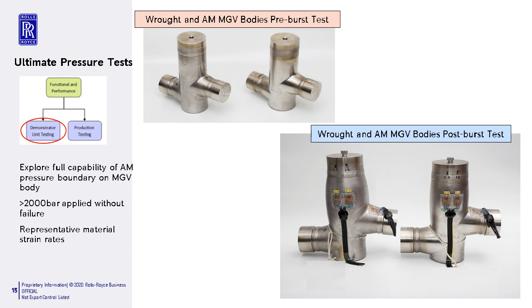And this rig was able to go up to around 2,000 bar. So we're really trying to blow up the valves. What we found was that both valve bodies retained the full pressure without failure, just experiencing a level of permanent deformation, which you can see from the image on the right there. You'll notice that the AM valve had slightly less deformation, which we believe was a result of the slightly enhanced proof stress properties that we previously discussed.